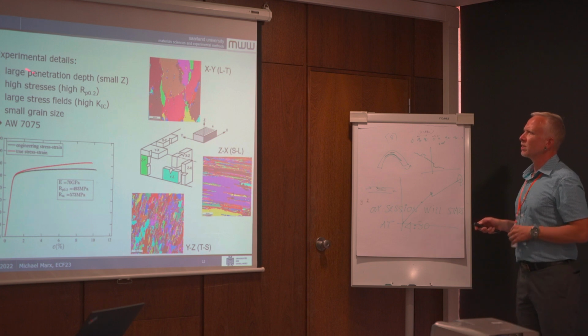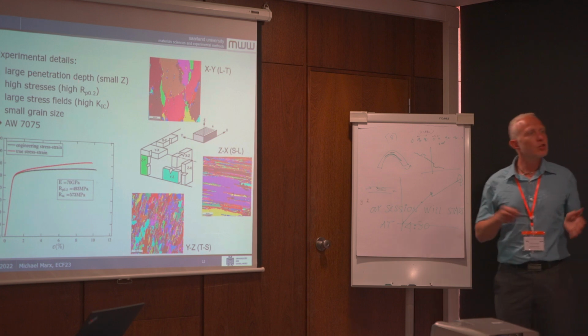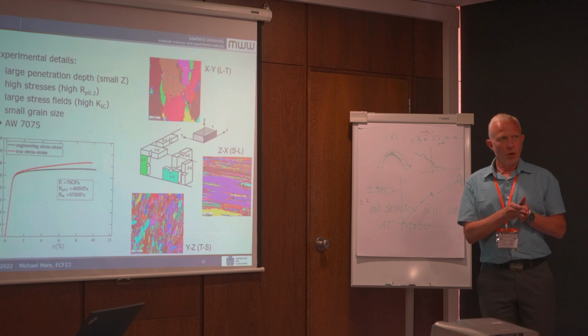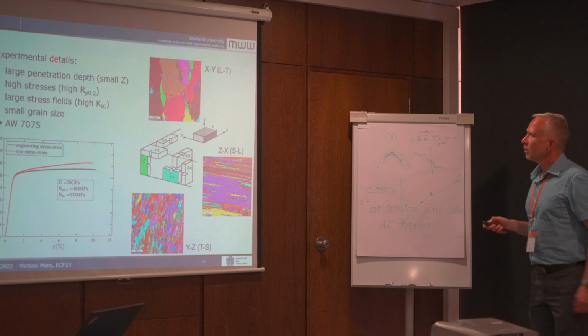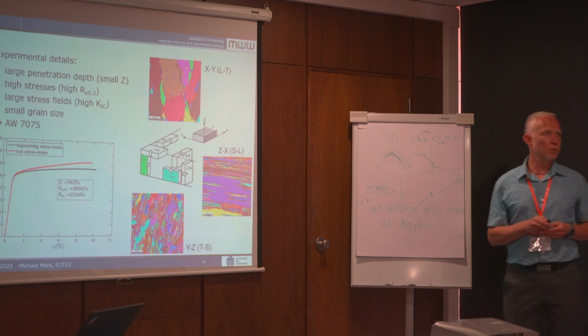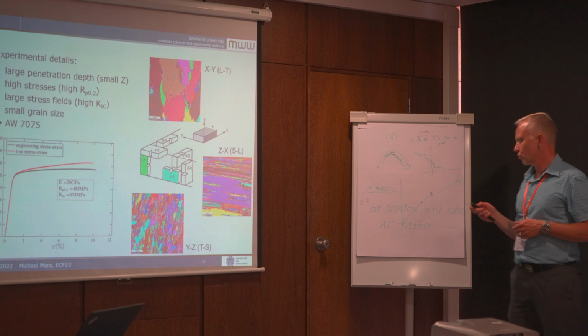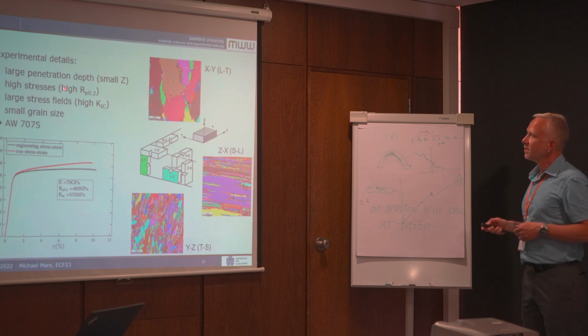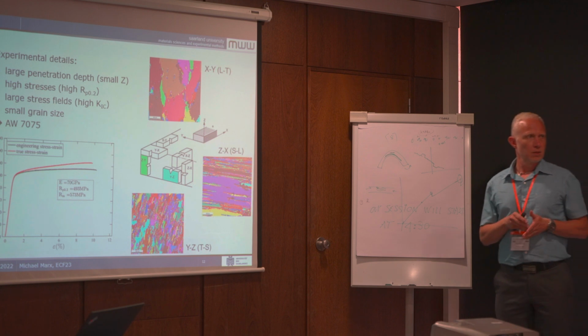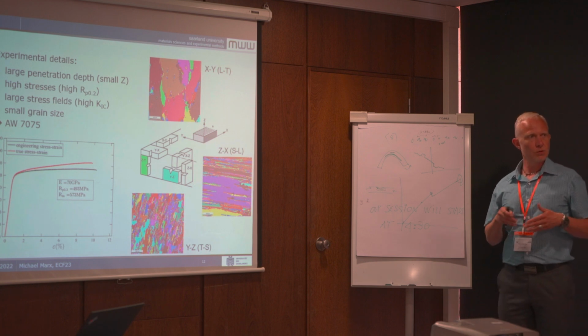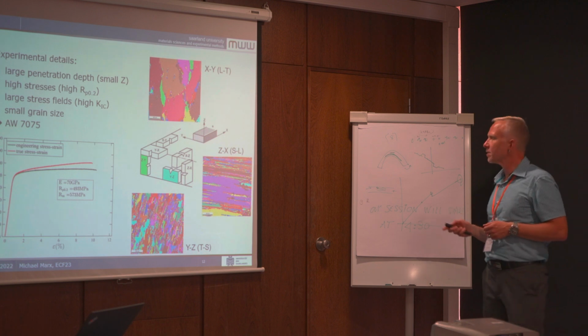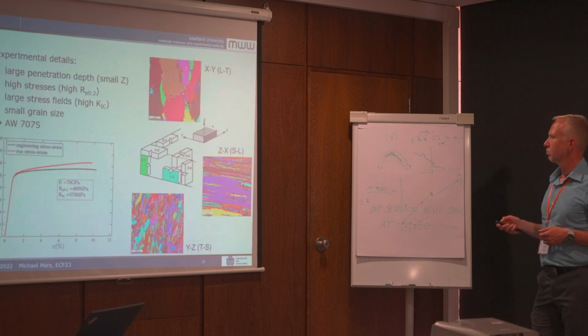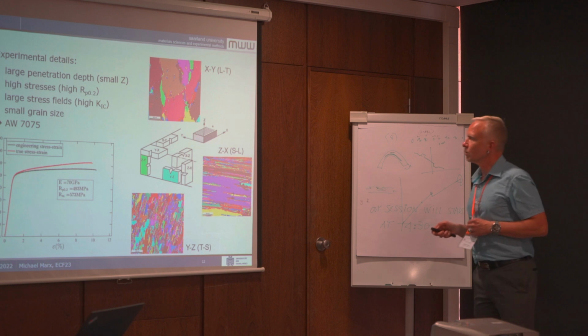What do we need? We need a large penetration depth, as large as possible, because we want to see, in the optimal case, through the whole specimen, which means we need a material with a small atomic number to get a low absorption of the X-rays. We need high stresses and large stress fields to be able to image this with our resolution of about 100 microns step by step. Therefore, we need a material with a high yield strength and a high fracture toughness to get large plastic zones and stress fields in front.